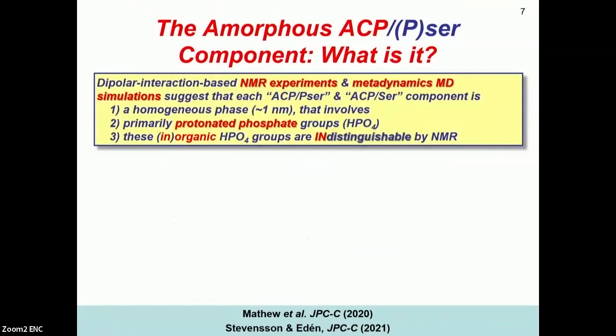So we have performed various NMR experiments along with metadynamics MD simulations to try to figure out what is the nature of this ACP PSER phase. And our main conclusion is that it's a fairly homogeneous phase, at least across a nanometer scale. And it involves primarily, along with calcium, protonated phosphate groups. An interesting issue here is that it's totally impossible to distinguish these phosphate groups by NMR in terms of organic or inorganic origin.